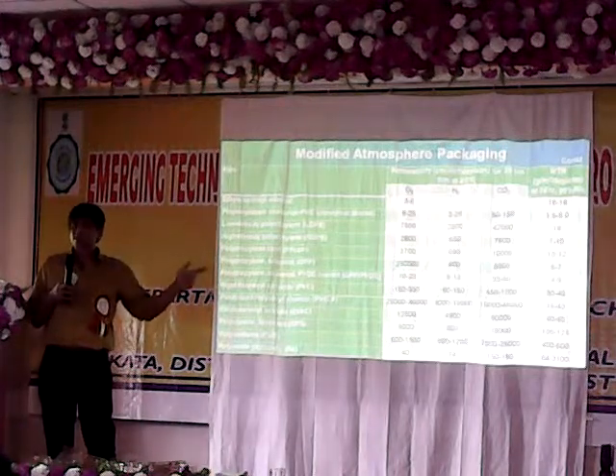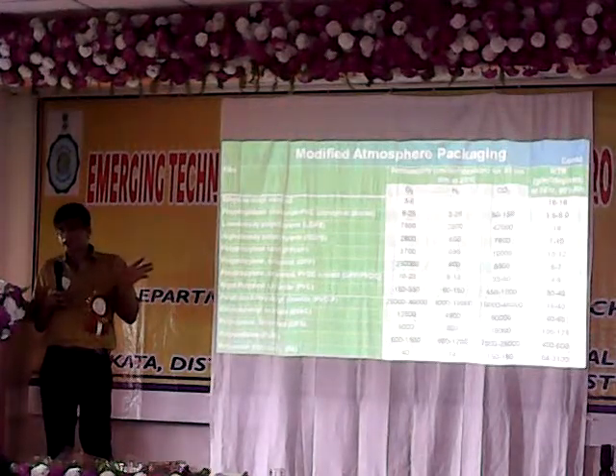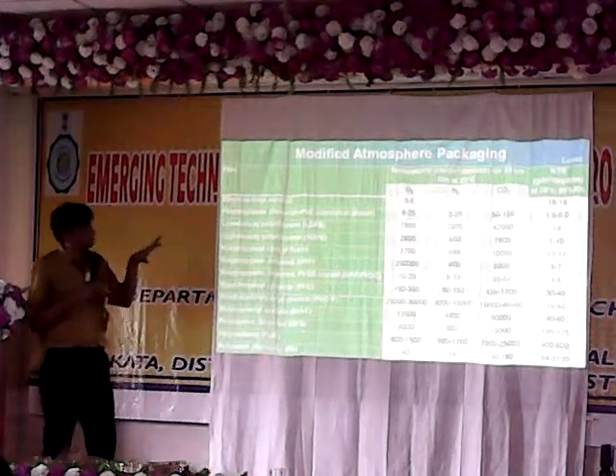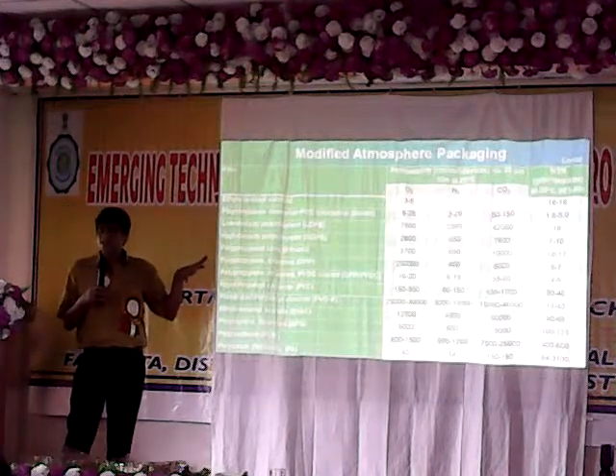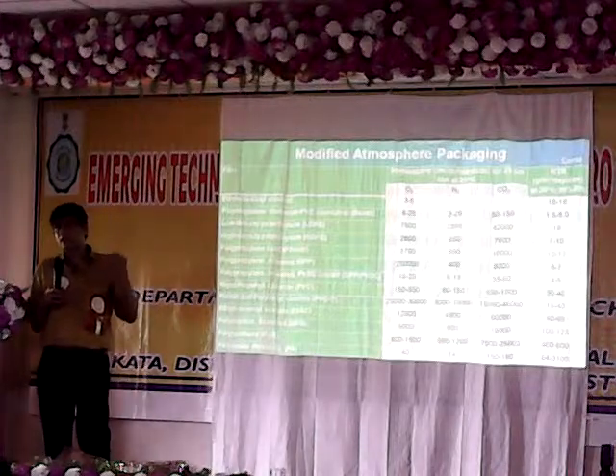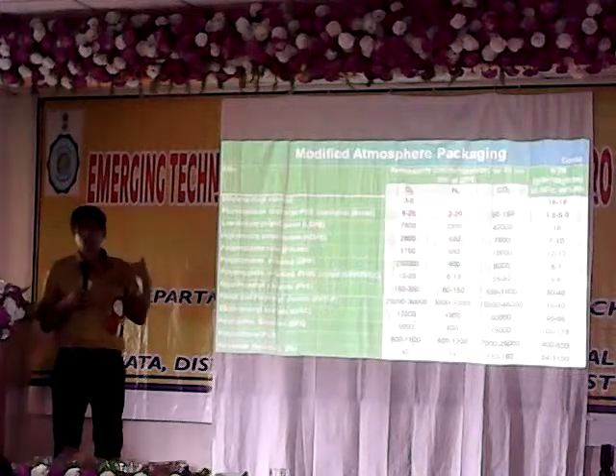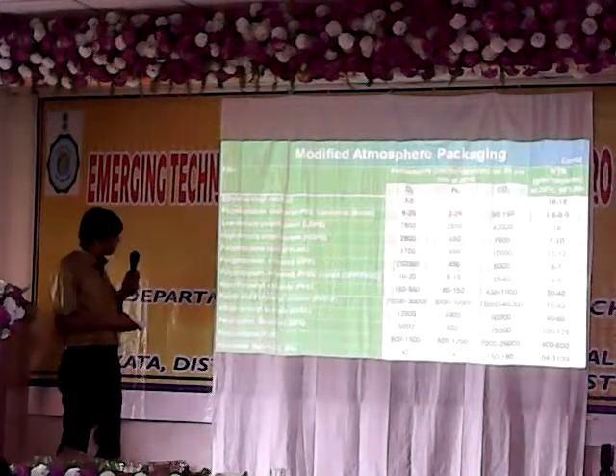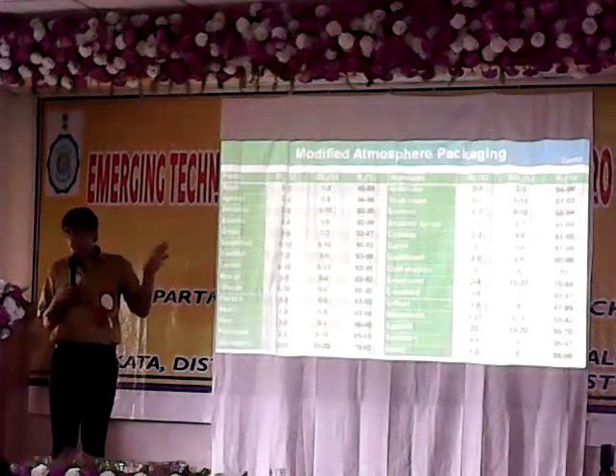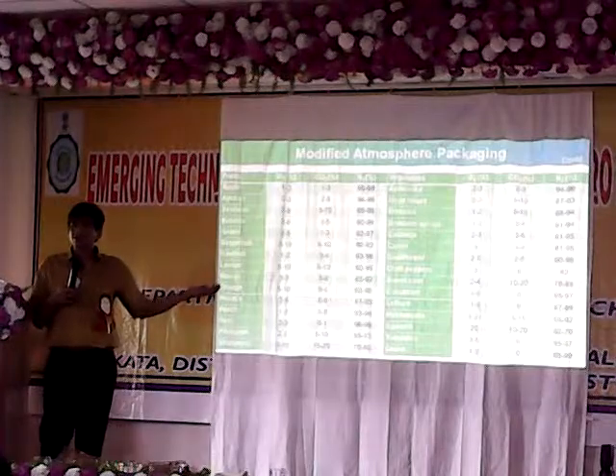Normally, for a good modified atmosphere packaging film, you have a permeability ratio of carbon dioxide to oxygen of about 5 to 10. So if the carbon dioxide to oxygen permeability ratio is between 5 and 10, you can think of that as a good film to be used as a modified atmosphere package.